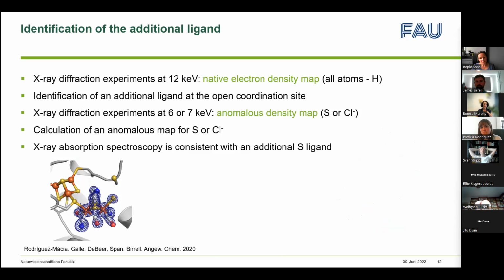So then we were still interested in why the enzyme is not sensitive to molecular oxygen, or what is the mechanism of protecting the active site against molecular oxygen. And we did X-ray diffraction experiments at 12 keV. And at this energy, the data can be used to calculate the native electron density map.